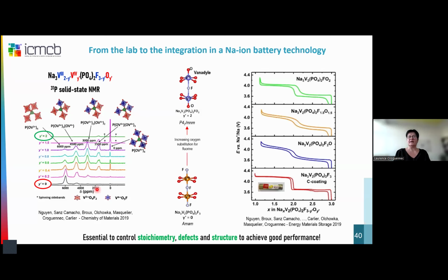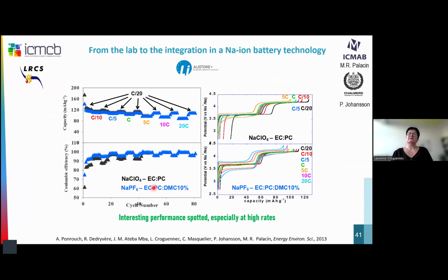And I wanted also to highlight that these techniques also here allows to really detect very small defects in these materials here. So already at that time, in collaboration with the frame of the ALISTORE network, we were able, here in full cells versus hard carbon, with collaboration with the group of Maria Palacin and Patrick Johansson, to demonstrate that this material was very good at high rate. You can see here in lab prototype, we had almost no loss of capacity moving from slow rate to high rate here.